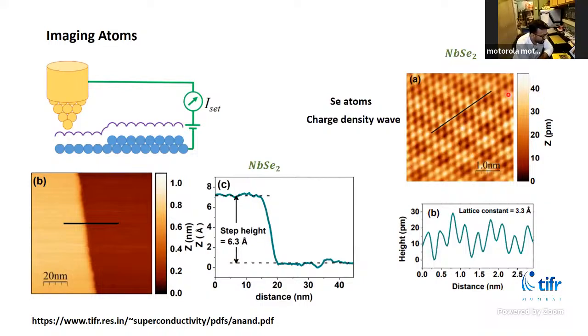You can see this. All these dots that you are seeing are selenium atoms. This niobium diselenide is cleaved in situ to preserve its surface so that the surface is not contaminated. And then when you move your tip in this fashion, it gives you such an image. You can see the bar here. It's 1 nanometer, and you can see the sub-nanometer resolution and the imaging of atoms. If you take a line scan, you can see the height varying as the tip is moving, going to an atom, going between atoms, then again following the same routine.